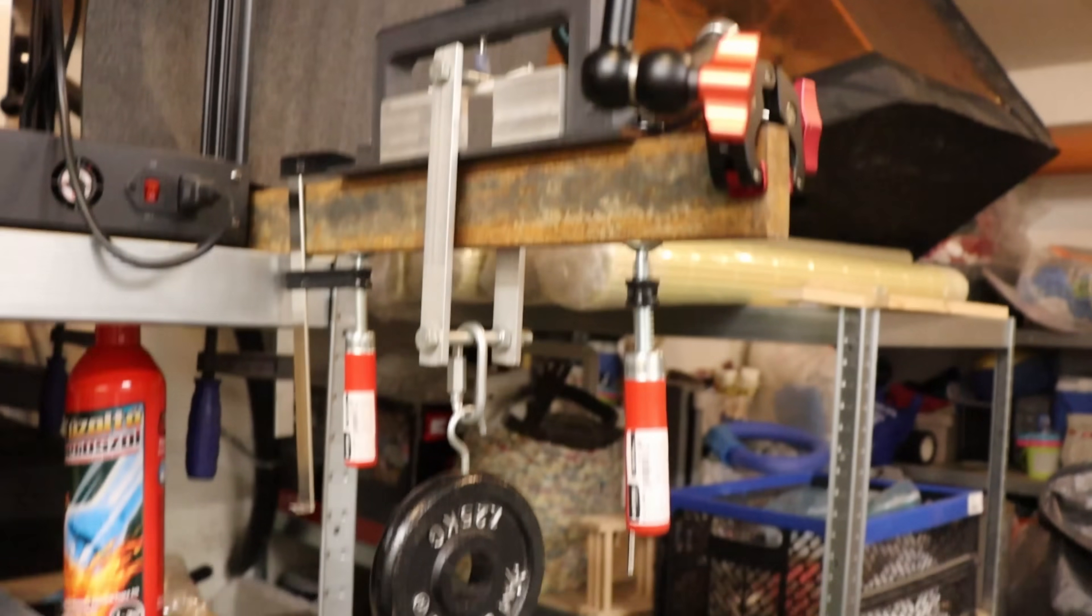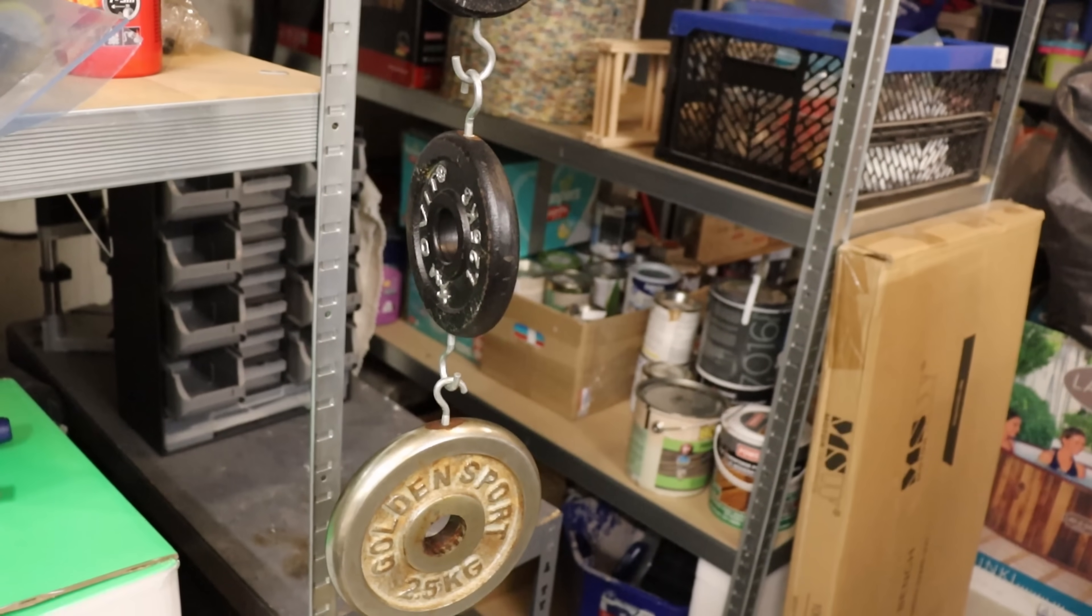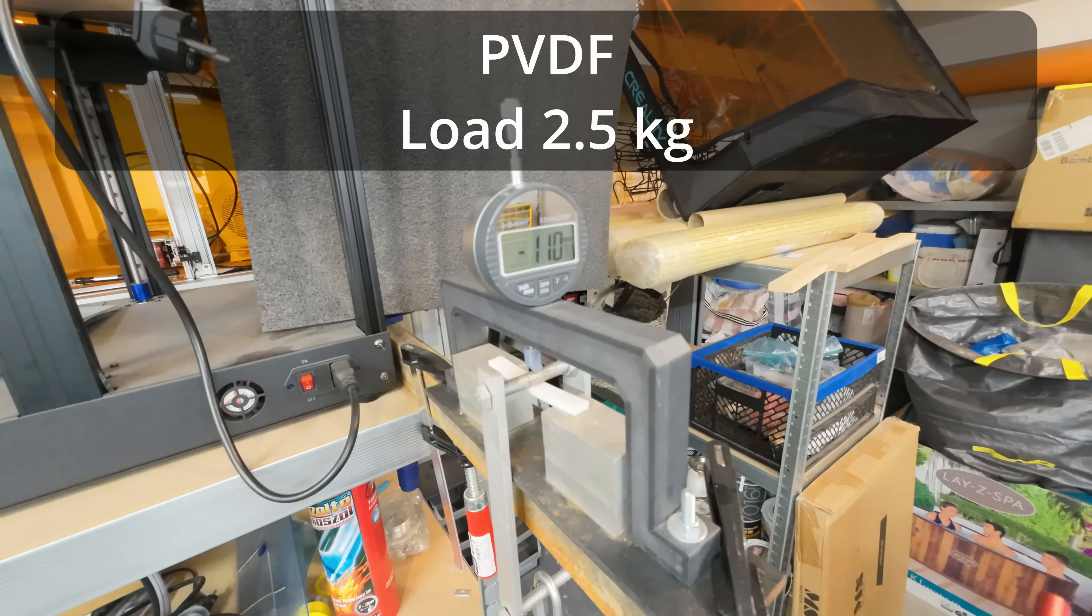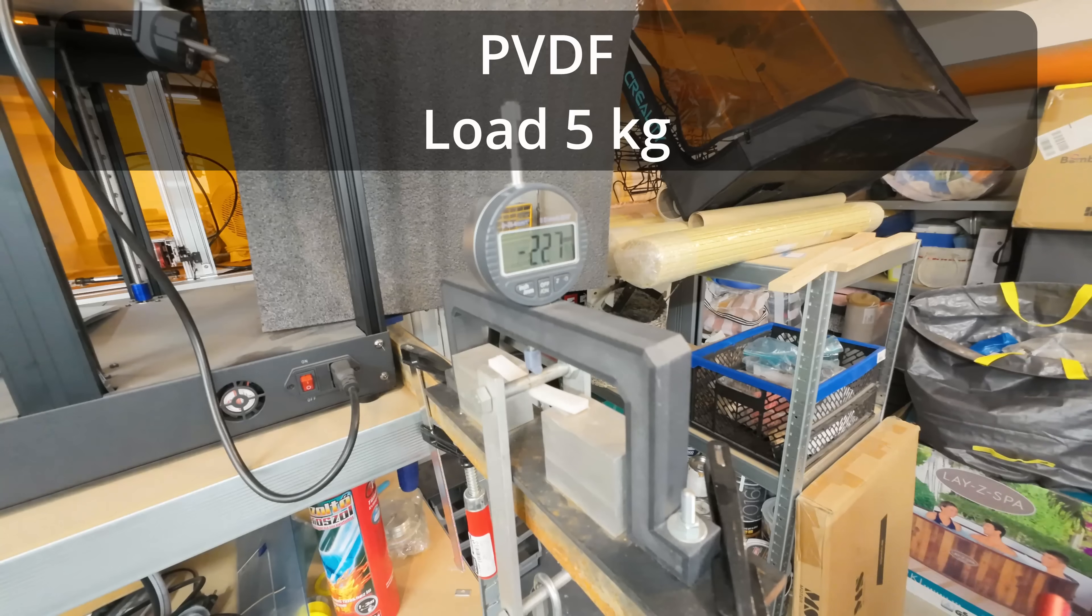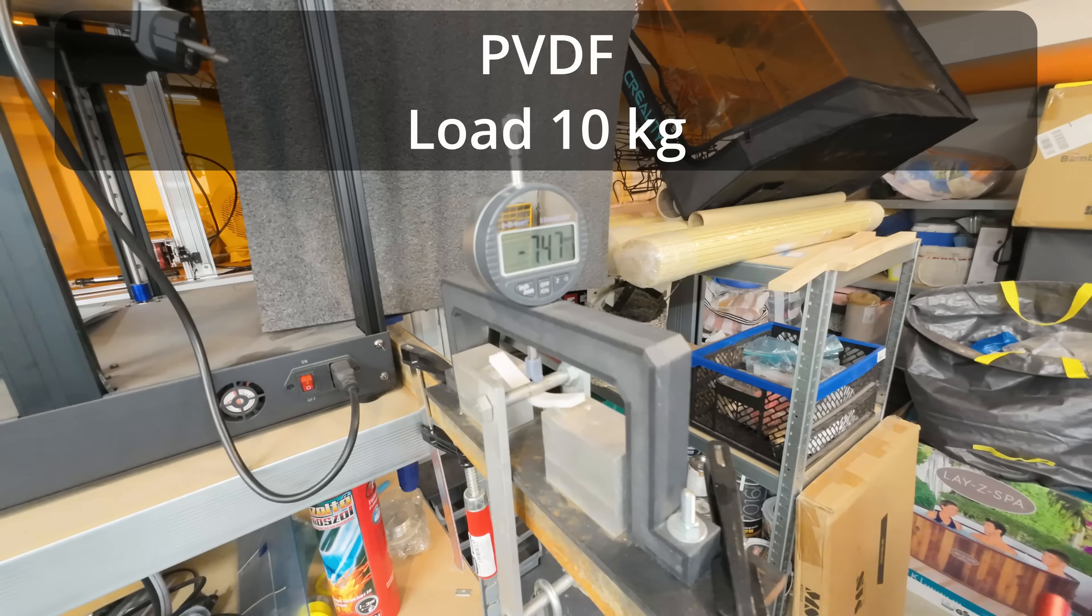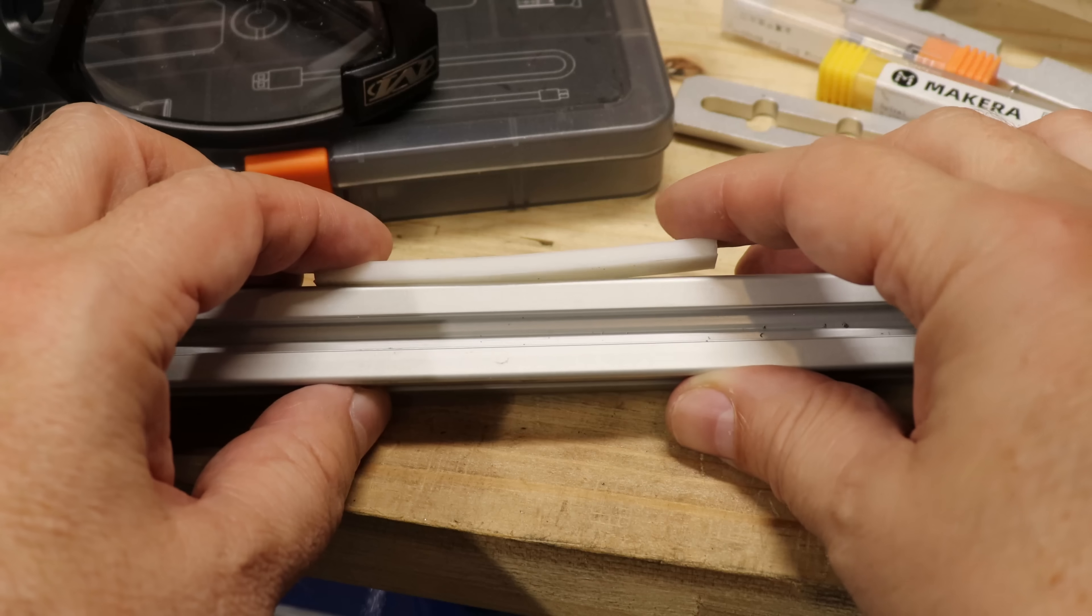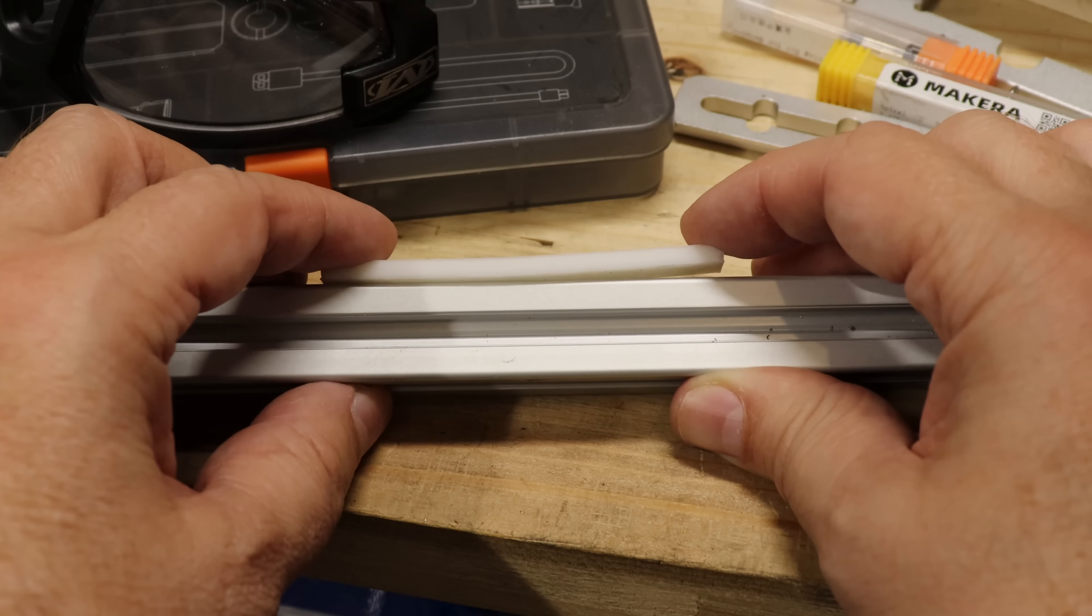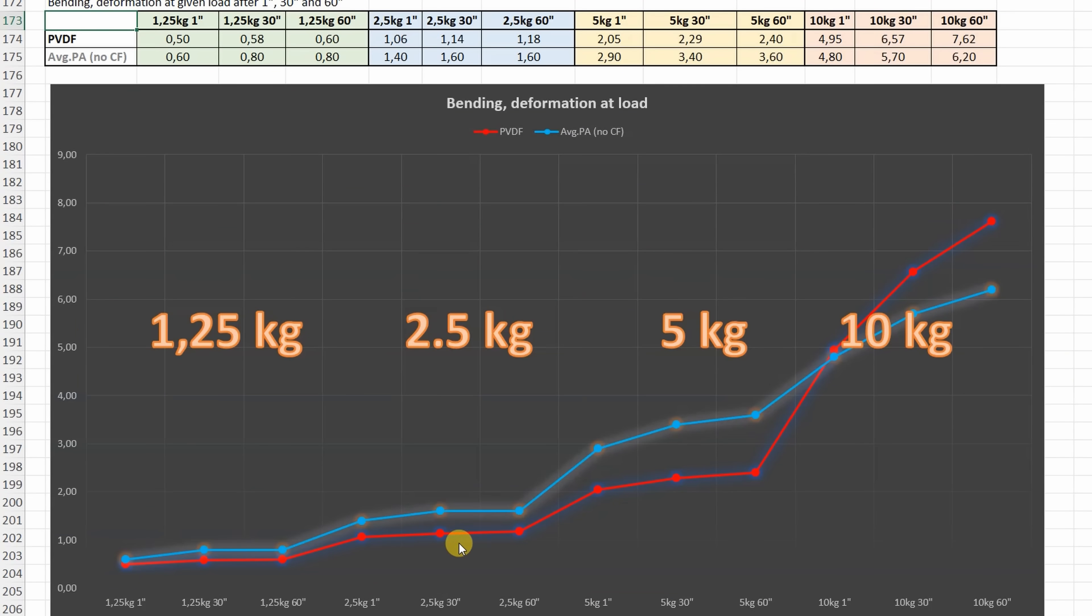3-point bending test, distance between supports is 50mm, and these loads will be placed one by one, and I am measuring the deformation after 1, 30 and 60 seconds. This is the deformation under 2.5kg, under 5kg, and even here I can see the constant deformation during the time, and this is 10kg, which definitely this material don't like. During the test it had huge deformation under the load, but now 5 minutes later, this is its permanent deformation. Wow, look at this graph. So PVDF which stands better the bending until some point, in this case until 5kg, but above of this this is completely lost. But even this 5kg is too much for this material, I can see a constant deformation during this one minute.